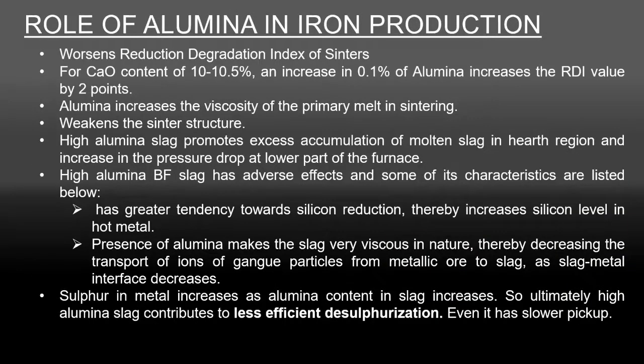Role of alumina in iron production. Alumina has its own effect on sinter. Most harmful effect is it worsens RDI value; for CaO of 10 to 10.5, increasing alumina by 0.1% increases RDI by 2 points. Alumina increases the viscosity of the primary melt. It weakens the sinter structure. It promotes excess accumulation of molten slag in the hearth region and increase in the pressure drop at lower parts of the furnace. It has adverse effects.